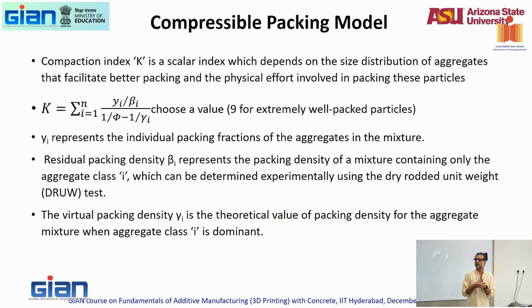There are several different models for packing. You can have monodisperse, polydisperse. You can have packing that's based only on packing densities, packing that's based on size and density, so many different varieties. But this is one kind of packing model that is computationally easier to implement. That's why I use it, so that when I give you the app finally for particle packing, it will have this model. What it does is take into account what's called a compaction index, which is simply a scalar number, which depends on the size distribution of aggregates that facilitate better packing and the effort involved in packing.